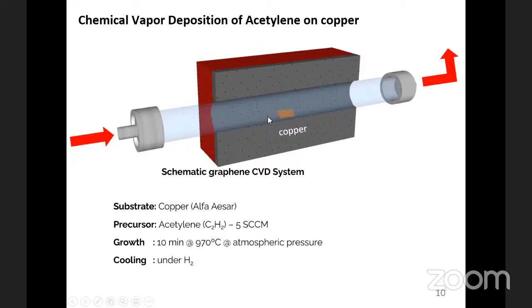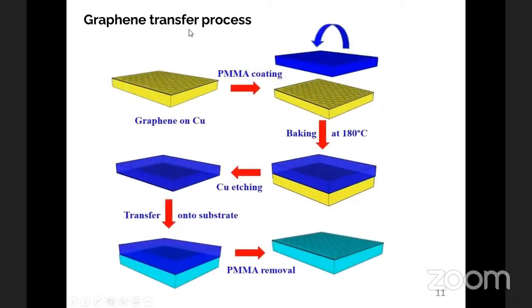So what happens when you flow acetylene and heat it up to 970, close to 1000 degrees Celsius? The acetylene is decomposed, and the decomposed carbon will segregate and form a graphene layer. The number of layers can be controlled using different parameters such as the growth time, acetylene precursor flow rate, and the cooling rate. There are many factors that determine the layer control over the process. So here I have grown the graphene on a copper substrate.